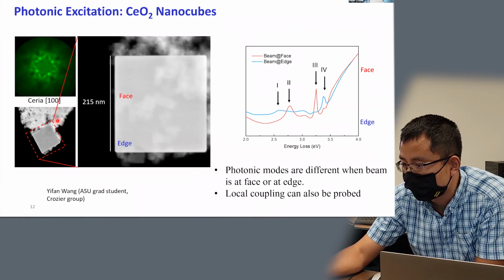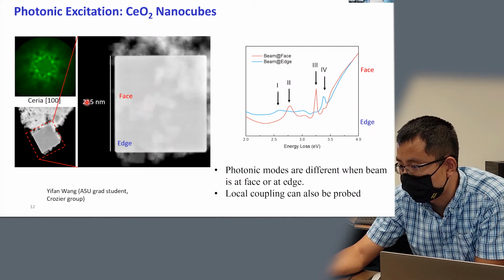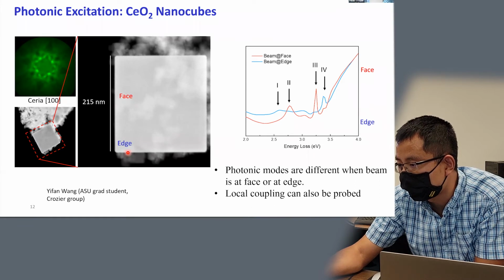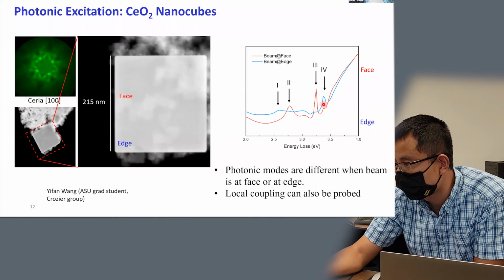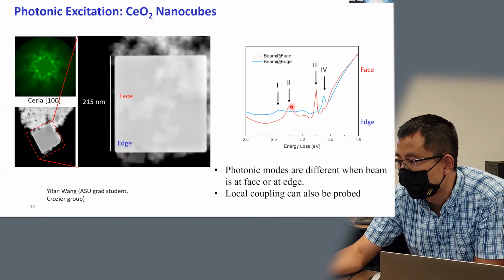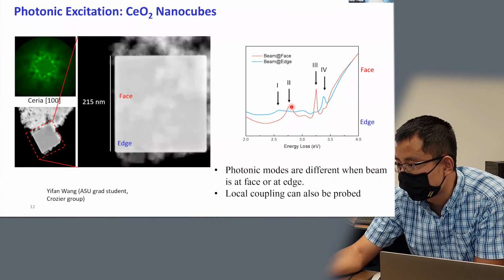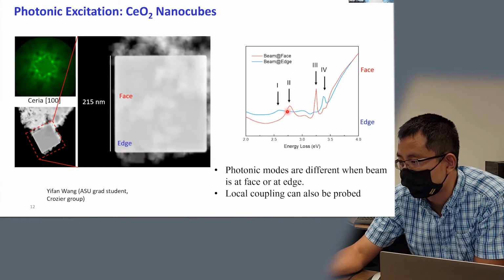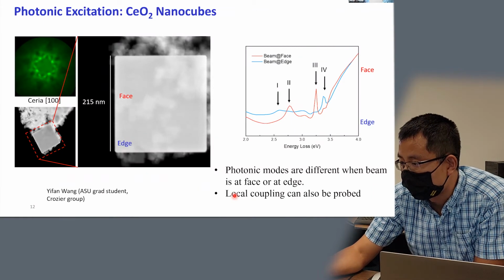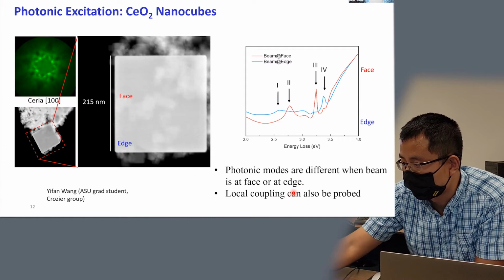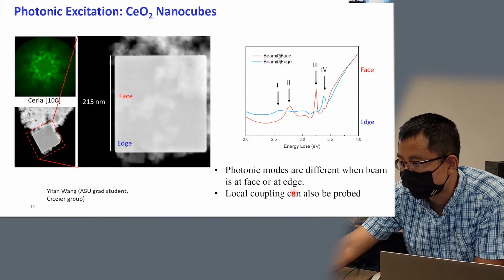On the left shows an image of the ceria cube, about 200 nanometers in size. And we can park the beam at different positions outside the cube, marked as face and edge. And then if you look at the spectrum to the right, you can see that the electron beam can excite and probe different modes when the beam is parked at different positions. And that means local coupling can be probed with the EELS technique.